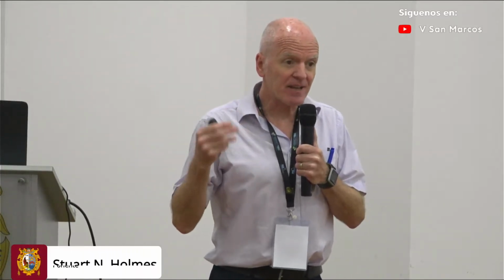Thank you. That's a good question to ask. We have what we think is some two-dimensional behavior. If you rotate the device in the magnetic field, it will respond to the perpendicular field component if it's two-dimensional. The problem is, in the three-dimensional films, they're only thin, and if you calculate the elastic mean free path, it's greater than the sample thickness. So you will get some so-called quasi-2D behavior when you rotate the sample round. That's the problem. But I totally agree, that's what I want to do in Grenoble next. Yeah, thank you, that's useful.